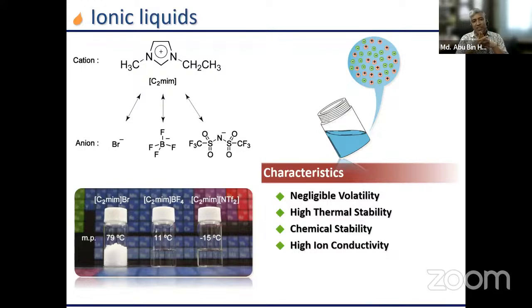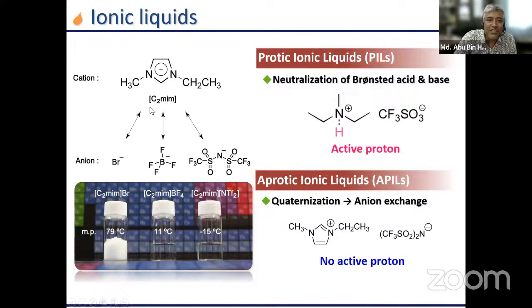For example, if we have a cation like this one, and we change the anion from bromide to tetrafluoroborate, and bis(trifluoromethylsulfonyl)imide. For these structures, the melting point is 79 for bromide, 11 degrees centigrade for BF4, and for this one the melting point goes below room temperature, minus 15 degrees centigrade. Such ionic liquids have negligible volatility, high thermal stability, chemical stability, and high ion conductivity. This is the cation, this is the anion. This combination gives rise to aprotic ionic liquids. There is no active proton here. So by quaternization and ion exchange, we can prepare aprotic ionic liquids.